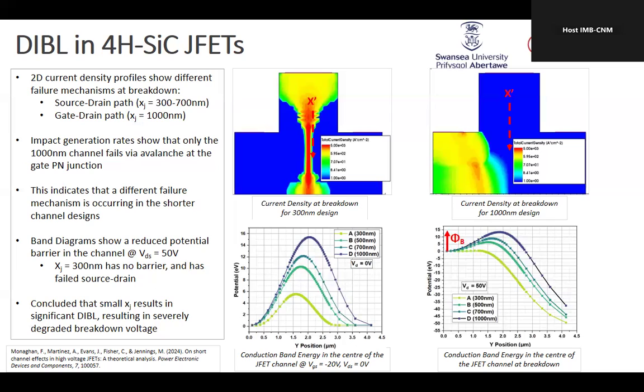And what you see is that if you plot the conduction band potential as a function of, you can see the cut line here, the X cut line, okay? So in this direction, we are cutting at X here. You can quickly see that the barrier to electrons from source to drain is much lower for shorter channel lengths. And moreover, when you go to about 50 volts, when you start putting high voltages on the drain, and the gate, I should say, is minus 20 volts in these simulations because it's a normally on device, right? When you go to higher drain potentials with the gate cut off, with the channel on, look at that, the barrier is pretty much non-existent for a short channel.